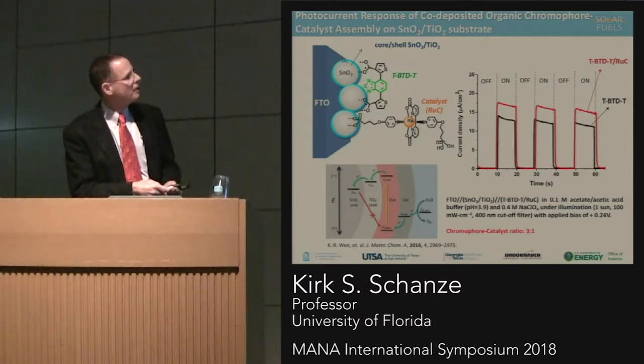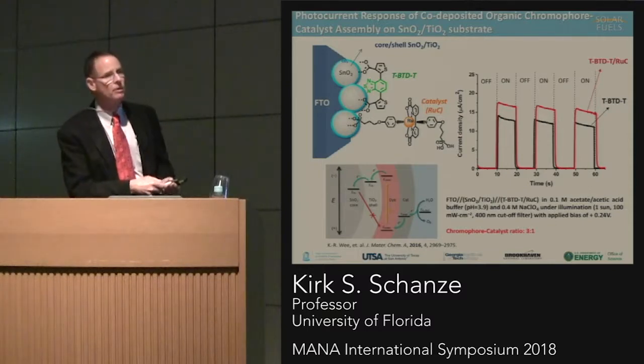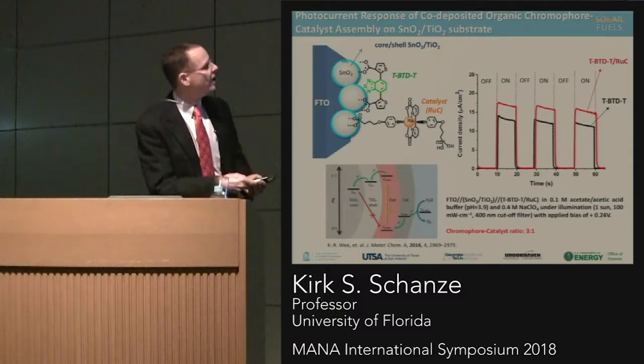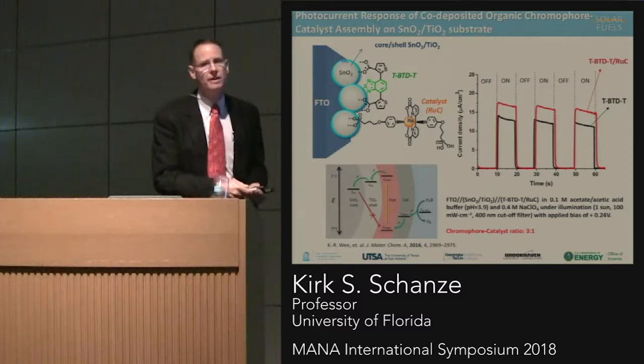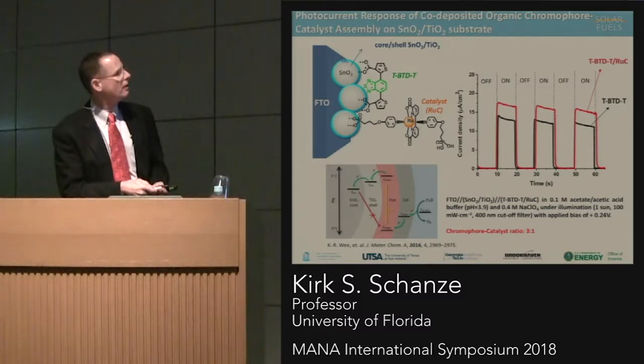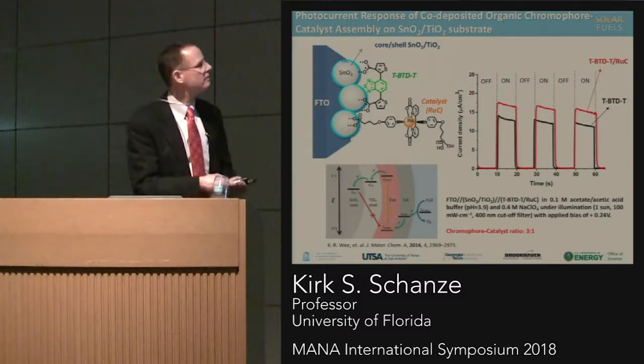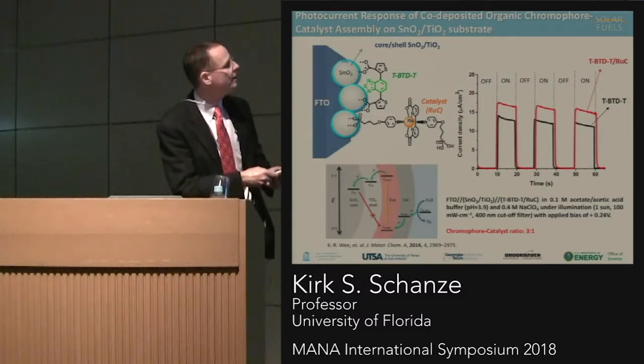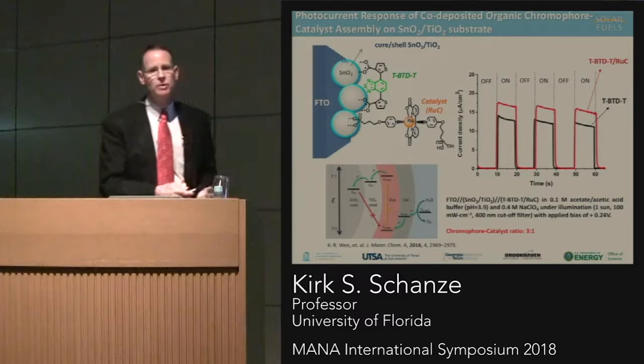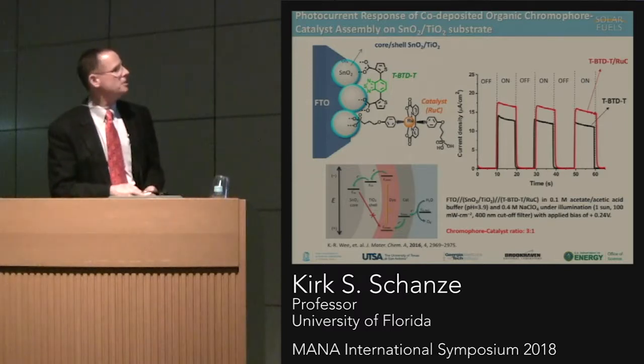And the photoelectrochemistry is shown here. In black is a control experiment where we have an electrode that has only the dye on it. When we add the catalyst, in this case, we see a very distinct enhancement in the photocurrent. And we do know quite clearly that photocurrent enhancement is due to hole transfer from the chromophore to the catalyst, which then activates water oxidation.